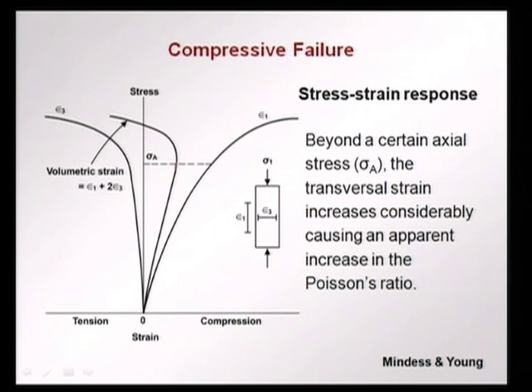increasing if we consider compression to be positive, the volume is decreasing, then suddenly the volume starts increasing when the axial strain continues to increase. That is, as the loading increases, we find that the volumetric strain now is decreasing or the volume is increasing. Even though you are compressing it, the volume increases beyond a certain stress, and this is because of the dilation or the cracks opening up, which is creating a bulging effect in the middle under uniaxial compressive stress. There is a bulging due to the cracking, which is called dilation or lateral expansion of the concrete. And this is something that is very typical of what occurs in concrete close to failure under compression.